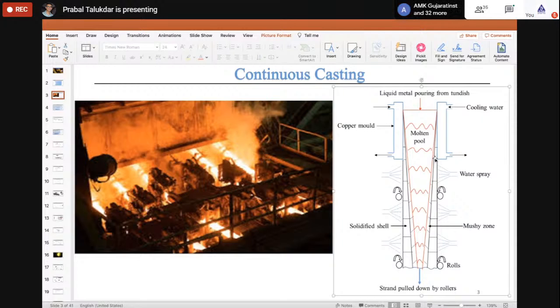Of course, it's not that nobody has done these calculations, but it depends on different cases. For the kind of industrial mold we came across with the industry, the calculations available in the literature, the kind of taper they advise, actually doesn't work in this mold, because the conditions are different. The taper depends on the rate of circulation of cold water. It depends on the casting speed also. The casting speed is basically the speed at which you get the steel out of this mold, right? Because at a certain rate you are getting the steel out of this mold, so that is called casting speed.